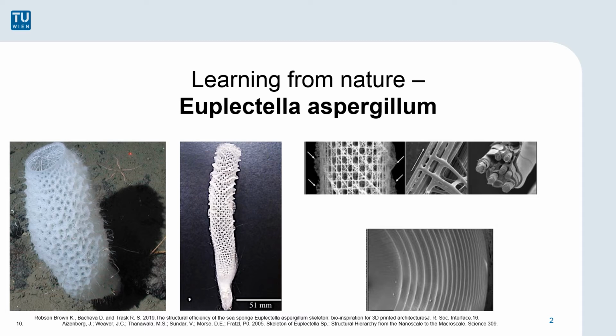If the outermost organic layer of the sponge is removed, one can find the siliceous skeleton of this animal. The skeleton is composed of so-called spicules. These are small rods containing 99% silicon dioxide and only 1% of organic proteins. Each spicule is made up of micron-thick concentric rings of silica separated by thin organic material layers. These soft material layers measure only 5 to 10 nanometers in height.